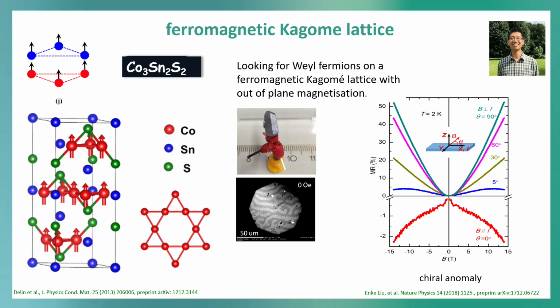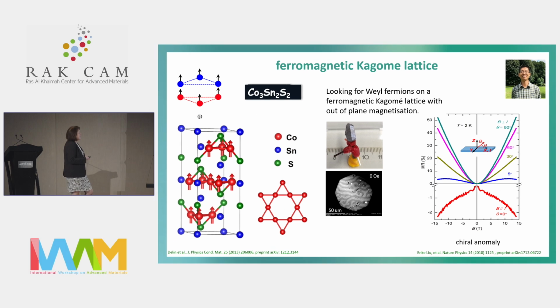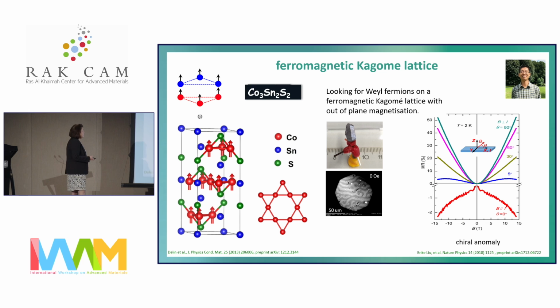We looked for a ferromagnet here because I also sometimes have applications in mind, like chirality. You know, I like quantum materials, but there should be something useful coming out. So this is, for example, a cobalt compound with a Kagome lattice where the spins are out of plane. If you have this anisotropic compound and the spins are out of plane, this leads to hard magnetic behavior. And this means in zero magnetic field, I still see this interesting quantum effect.